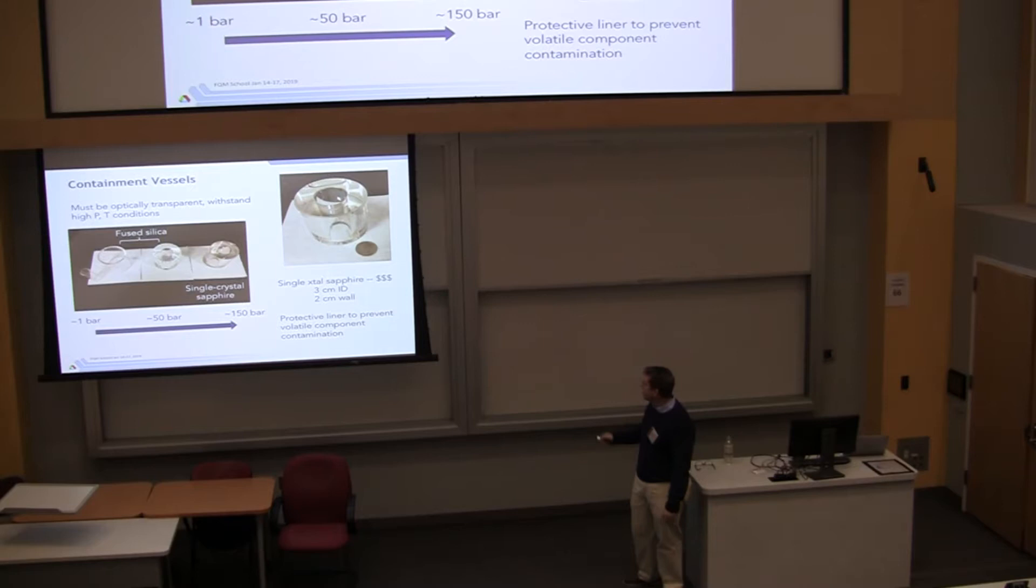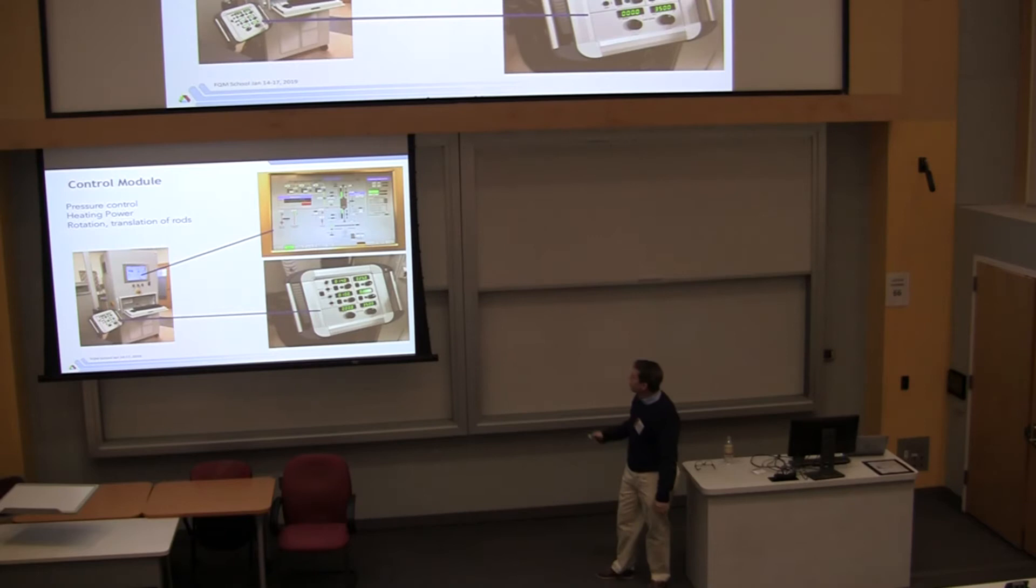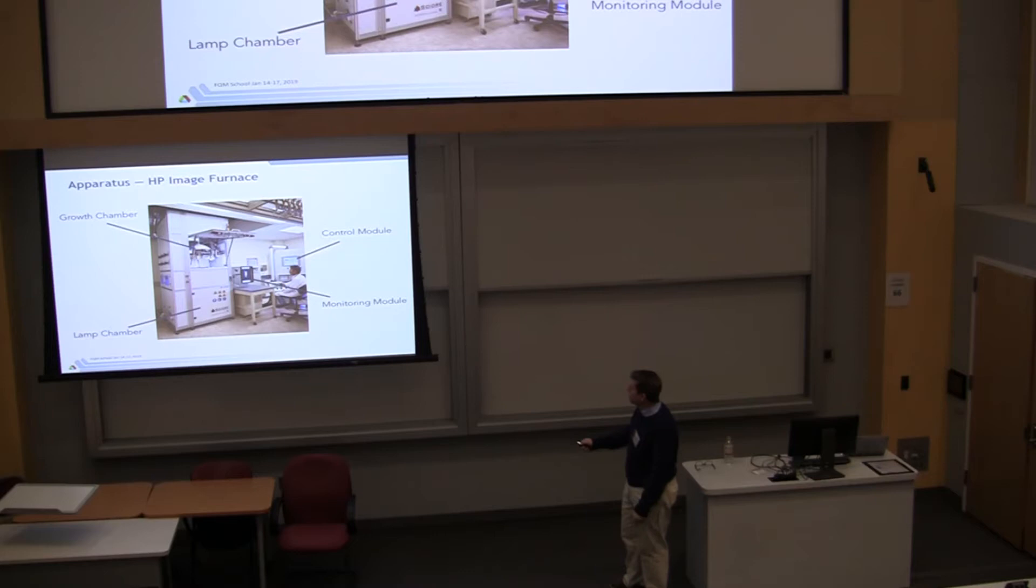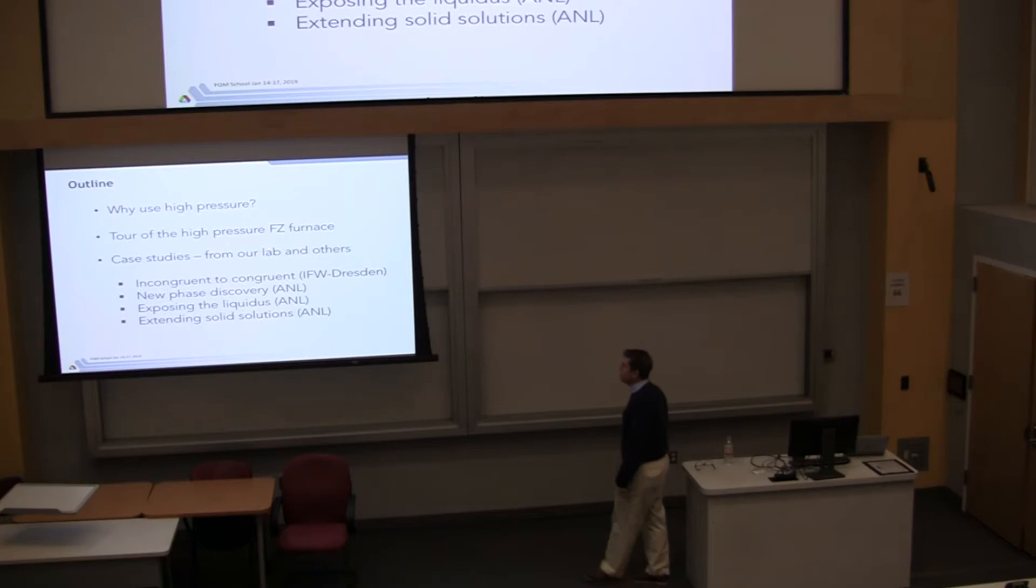Here again is the geometry in comparison to the two mirror horizontal. What do you guys have here? Four mirror furnace. I've got a two mirror furnace I've used for 20 years. It still works beautifully. And then this vertical geometry here that has been adapted for the high pressure system. So we have a lamp down here. The lamp sits at the bottom, the bottom focus mirror. It can get you to 2,800 degrees if you use a pretty big lamp, even at 150 bar.